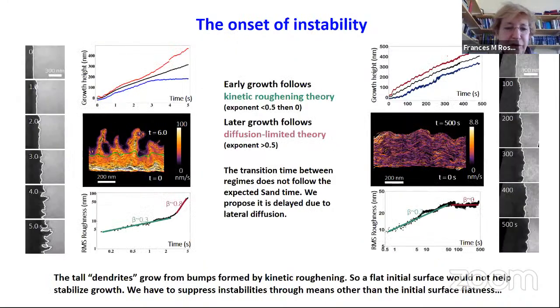We can compare growth under different conditions. We can look at the height of the peaks and the valleys. We can look at the roughness and how that evolves with time. And we can compare with kinetic roughening theory or diffusion limited growth. We can evaluate what the exponents for this roughness versus time log-log plots are expected to be, and then we can match this with the behavior that we see under different conditions. And what we find is that, again, as another diffusion process comes into play, the transition time between these two regimes is not what you'd expect, and lateral diffusion is an important factor here.